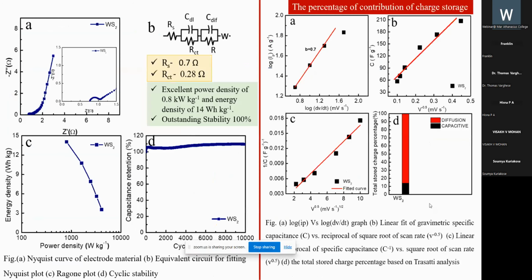Coming to impedance analysis, the solution resistance is only 0.7 ohm, and the charge transfer resistance is less than 1, that is 0.28 ohm, which shows the better conductivity of the material. The device shows an excellent power density of 0.8 kilowatt per kilogram and energy density of 14 watt hour per kilogram. Over a large 10,000 cycles, it shows 100% stability. The percentage contribution shows the presence of both EDLC and pseudocapacitance.